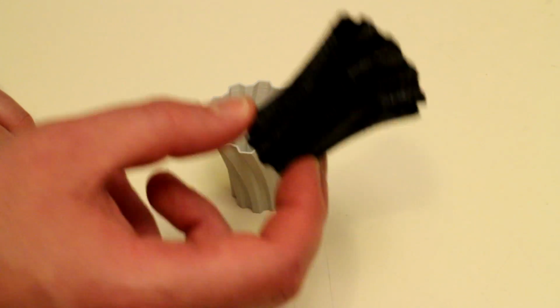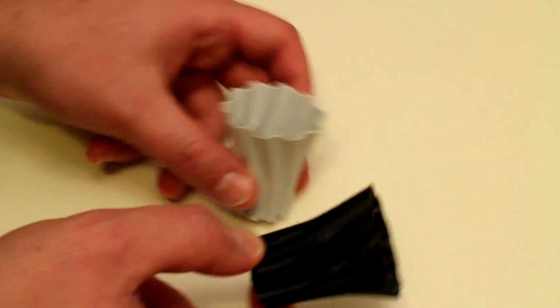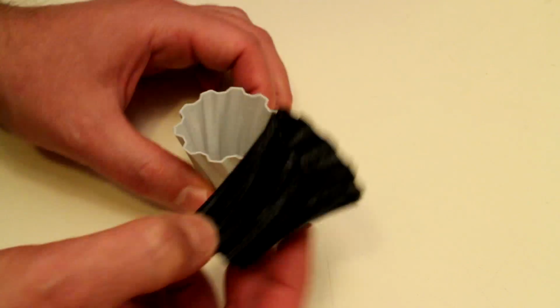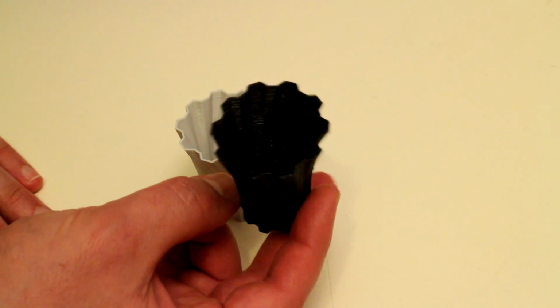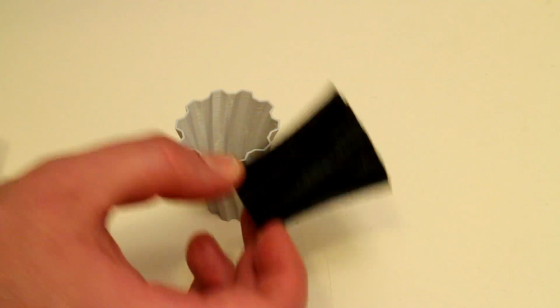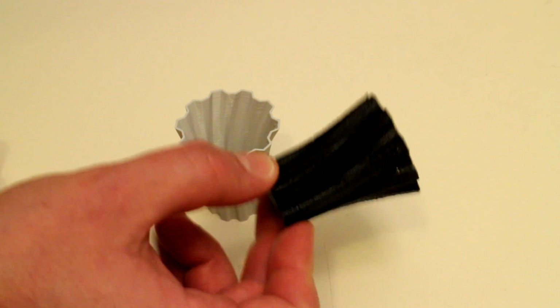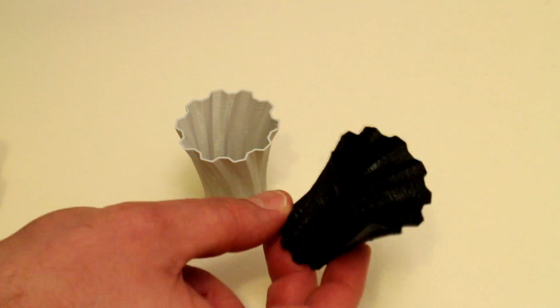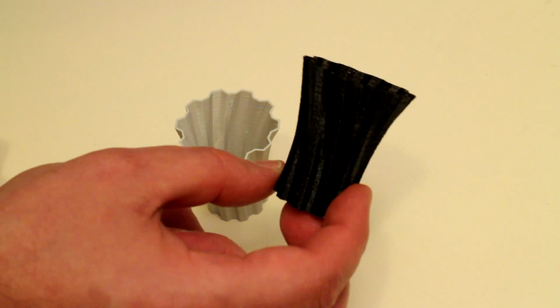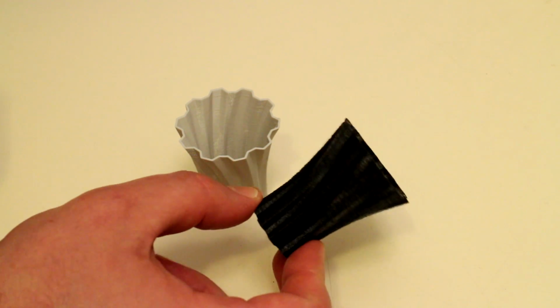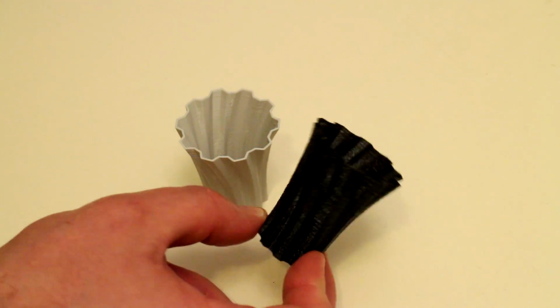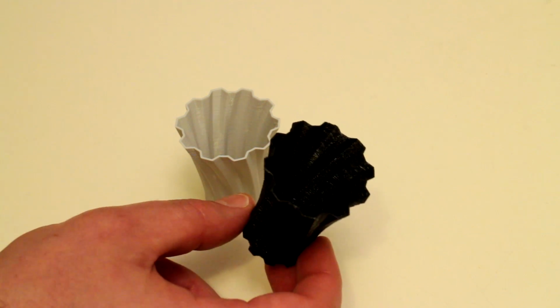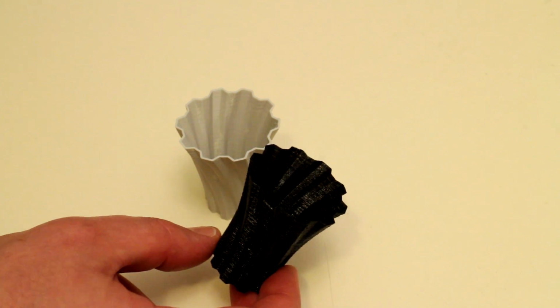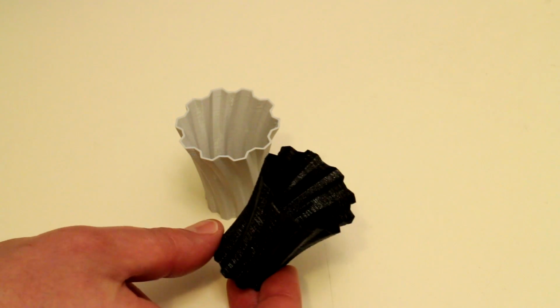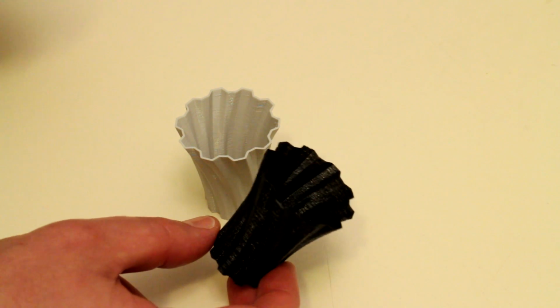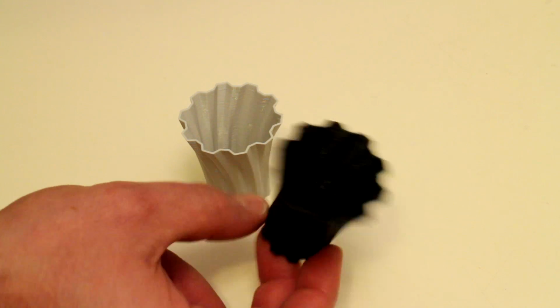And I also had to decrease the print speed from the 40 millimeters a second that I can print this at down to 20 millimeters a second. So the E3D and the Bowden at 1.75 millimeter really had troubles extruding this Flex TPU filament at a constant rate without under extruding. So if you have to increase your temperature and reduce your print speed, that's a sign of under extrusion, and I've had to overcompensate basically to print this.